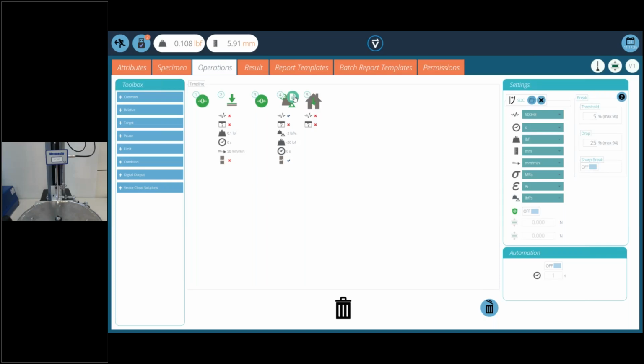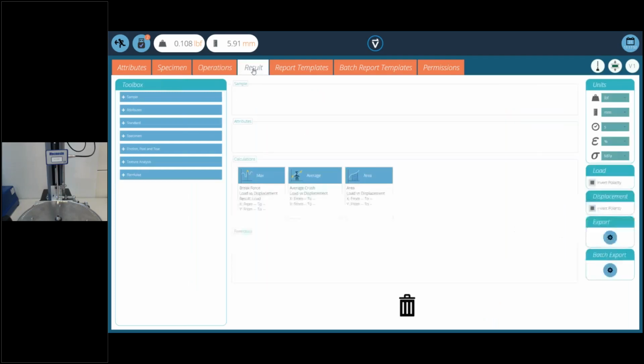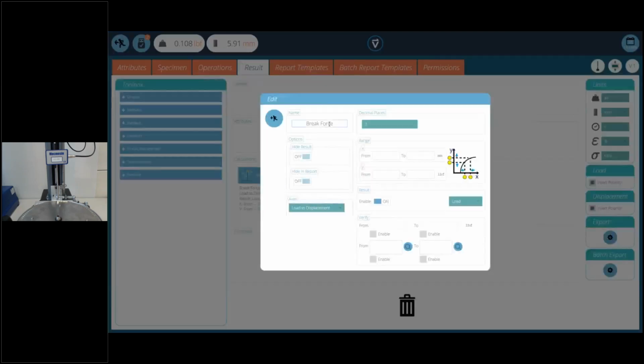Once the test completes, the crosshead returns home. And the only other thing I'm going to change here is to take a higher data capture rate, or data acquisition rate, or sampling rate, so we capture the break value as soon as it occurs. It essentially makes the break detection a little bit more sensitive. And then in our test results, we're looking for the maximum, which we're calling our break force here.